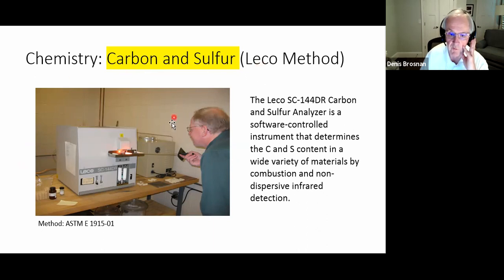The standard method throughout the world is the LECO method. The instrument named LECO lent its name to the method. And that means that we simply insert the specimen and burn off the sulfur and the carbon. And there's an infrared means of detection of the sulfur gases and the carbon monoxide, carbon dioxide that's emitted in igniting that specimen in air. And that tells us how much carbon is there. This is a standard method in analysis of materials. And so you can look up the method if you're interested in it. But just notice that carbon and sulfur are not determined accurately, or maybe not at all, by X-ray fluorescence.